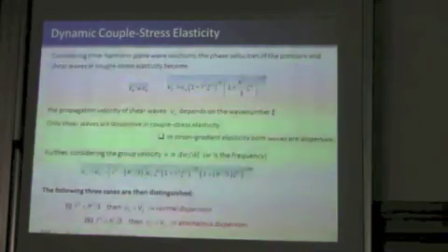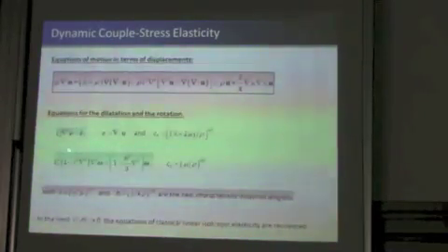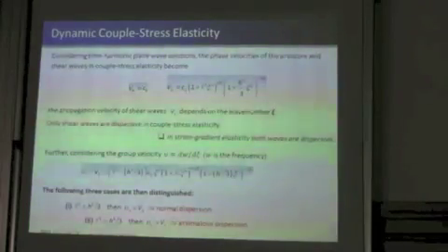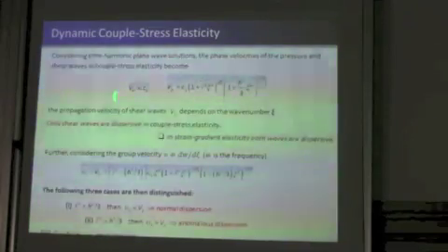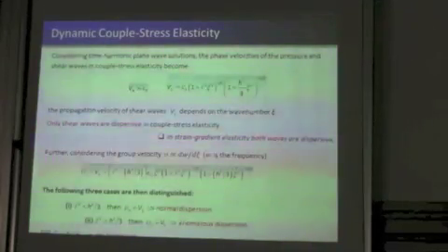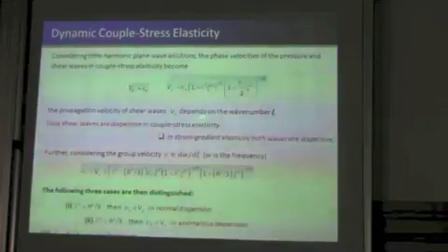Now, the fact that only the rotation is governed by a higher order PDE, and the dilatation by the classical equation, means that the pressure waves in coupled stress elasticity are not dispersive. Indeed, by considering time harmonic plane wave solutions to the previous equations, we obtain the phase velocities for the pressure waves, which are the same as in the classical theory, and for the shear waves, where we see that the velocity of the shear waves depends upon the wave number. So we see that only shear waves are dispersive.